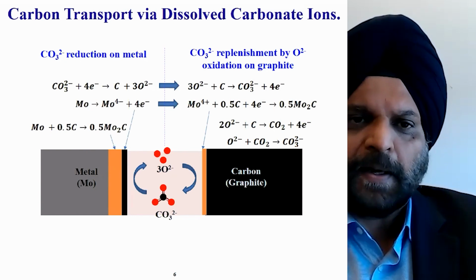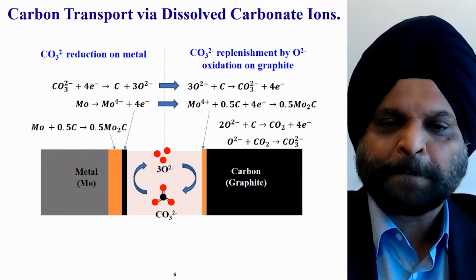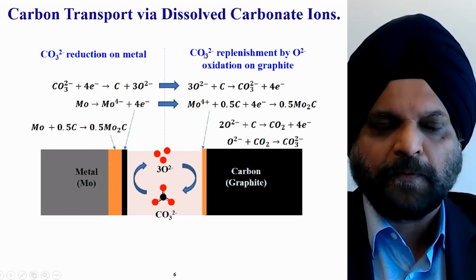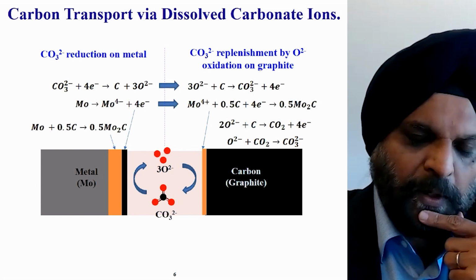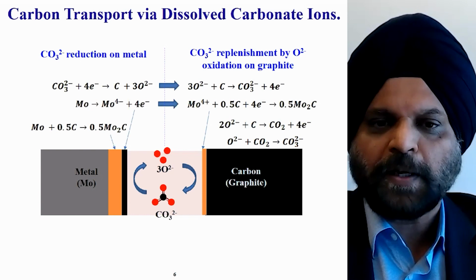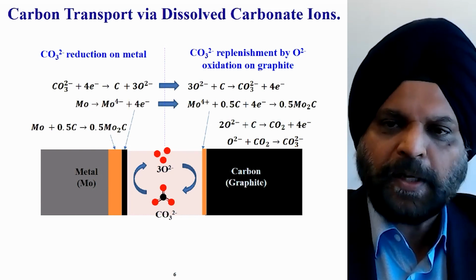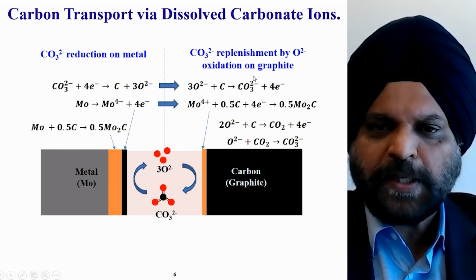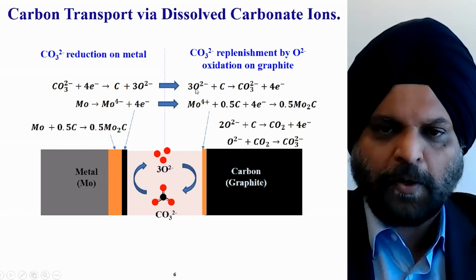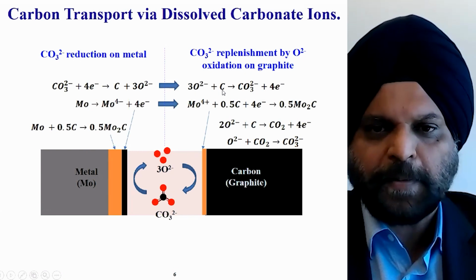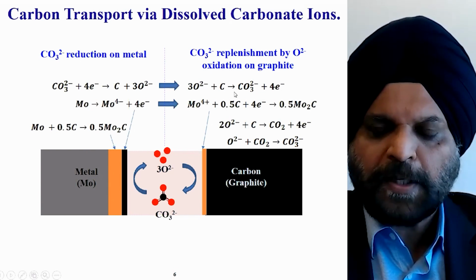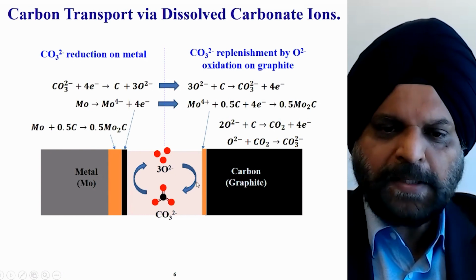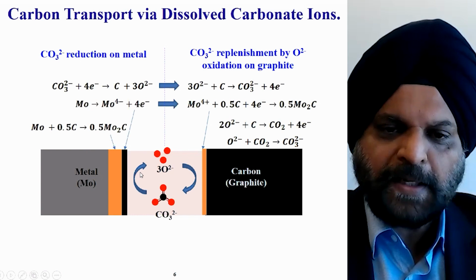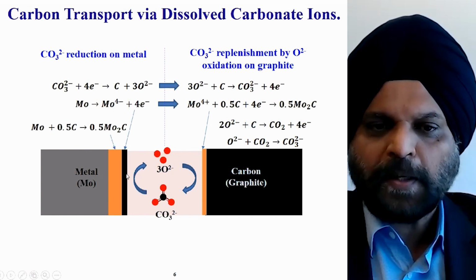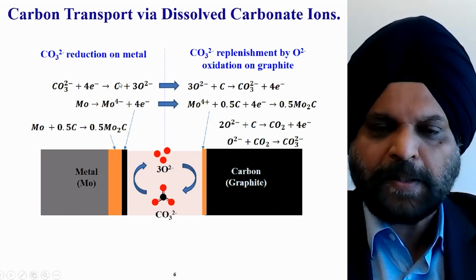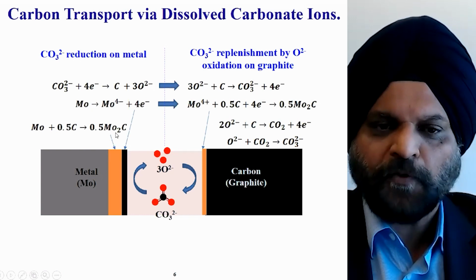Can carbonate actually be generated in FLiNaK? The concern we had in mind at the beginning was that oxides can come from, for example, dissolution of native oxide from the metal surface, or from some other impurities. Those oxides can react at the operating temperature with carbon or graphite, which is present in MSR-type designs, giving you carbonate ions in the solution. These carbonate ions can transfer carbon to the metal surface, where it gets reduced to elemental carbon, which is then available to the metal to form metal carbides.